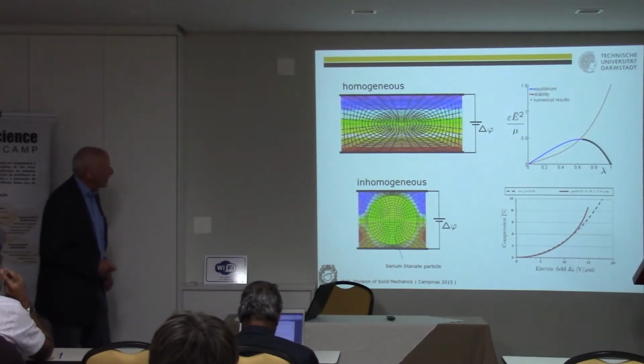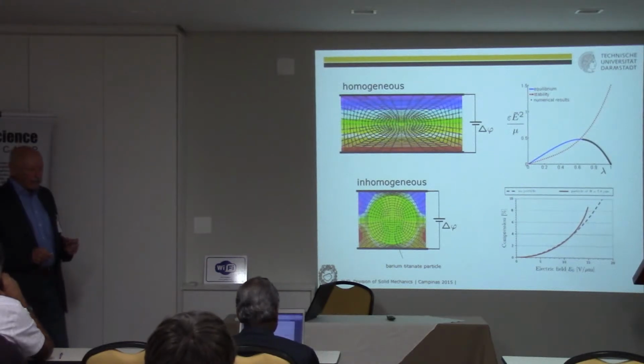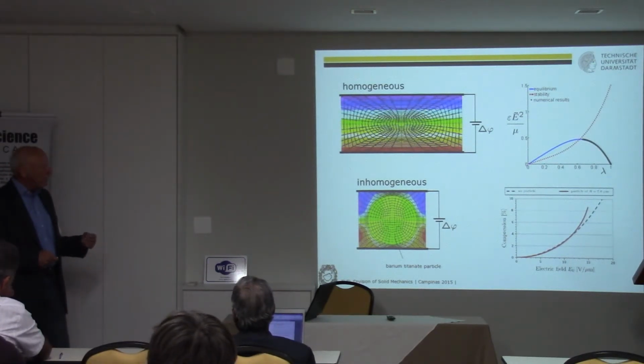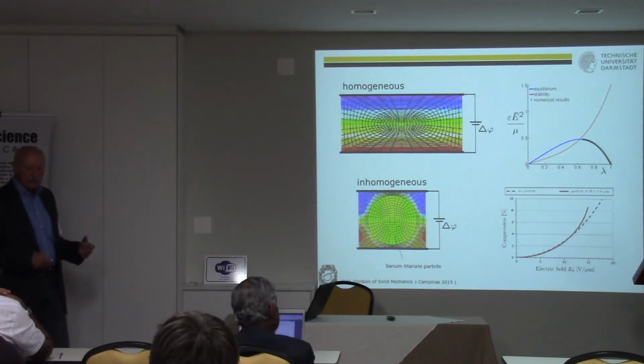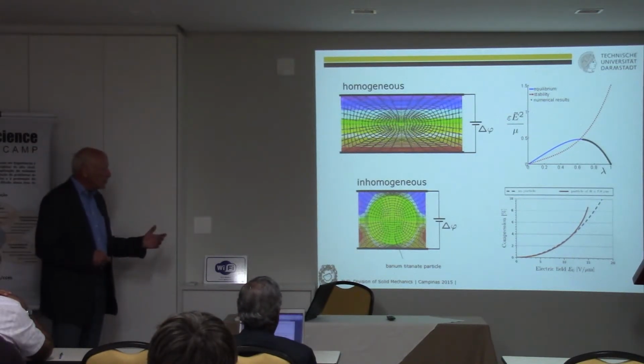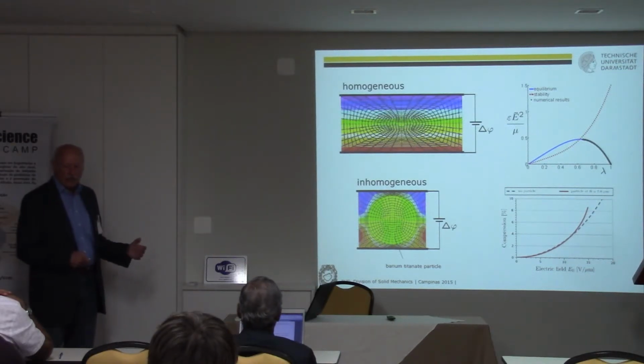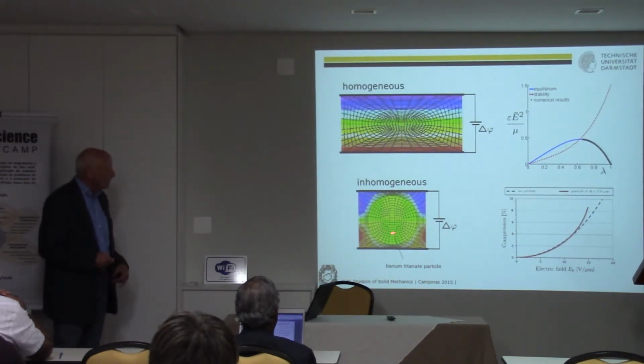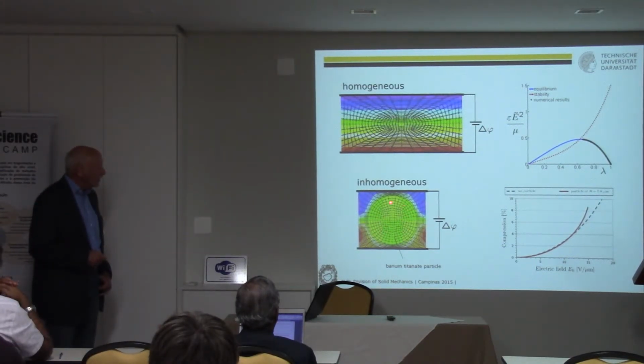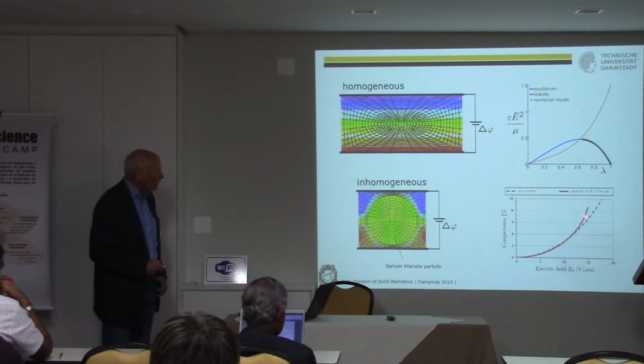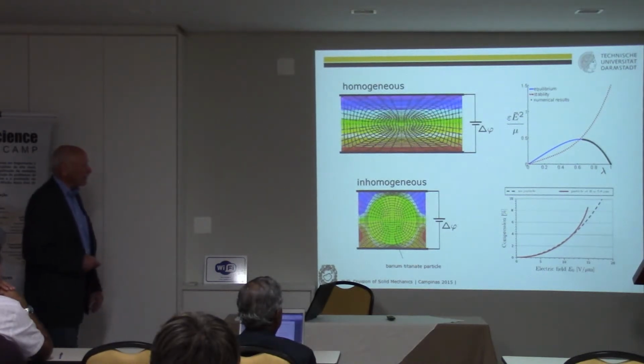And what you can do is you can put into the material piezoelectric material. Then you have a composite. And with this you change the overall electric material constants. And here we have done it only for one particle, a barium titanate particle, where we have the electric constants, and put it into the polymer, and what you see, if this is a red curve, then you get a much better, in this regime, a better compression or a stronger effect.